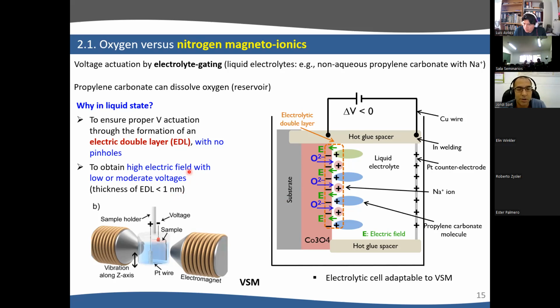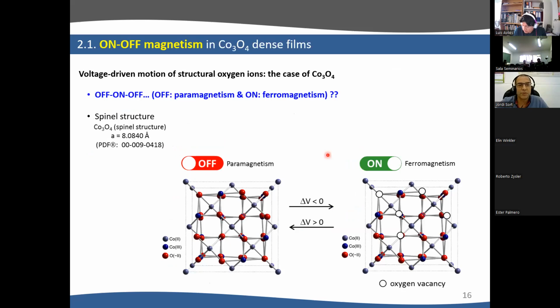Another advantage of this electric double layer formation is that if instead of a thin, dense film, you immerse there, for example, a nanoporous alloy, this liquid can penetrate inside and there are no pinholes, right? So you can actuate the whole structure like a sponge. We have some papers on this, which I'm not going to talk about, but if you're interested, I'm sure you can find them. So now let's move to cobalt oxide.